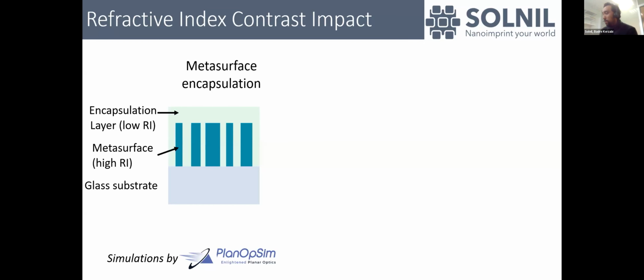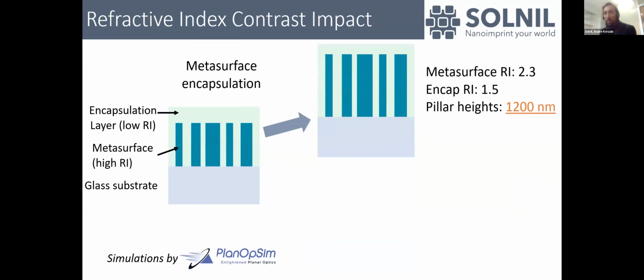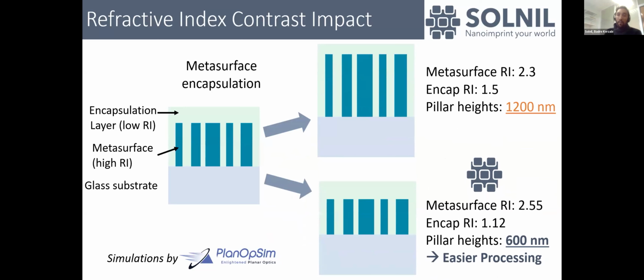So if we take an example, which was done with the help of PlanOpSim for the simulation: if you want to make, let's say, a design for visible light at 520 nanometer, if you use a material with a refractive index of 2.3 and an encapsulation layer of 1.5, you end up having to etch pillars with a height of 1.2 micron. On the other hand, if you can increase the refractive index contrast, so if you can go to a refractive index of 2.5 for the metasurface, and reduce the refractive index of the encapsulation to 1.12, now you need only 600 nanometer pillar height. So it has a huge impact on the processing. Using this wide range of refractive index allows you to simplify your process.